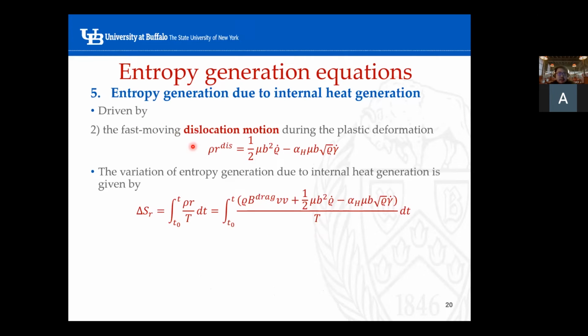Another term, the dislocation relative motion during the microplastic deformation, is given in this term. In this term, we also have a shear strain rate term. So combining these 2 equations, the first drag mechanism...